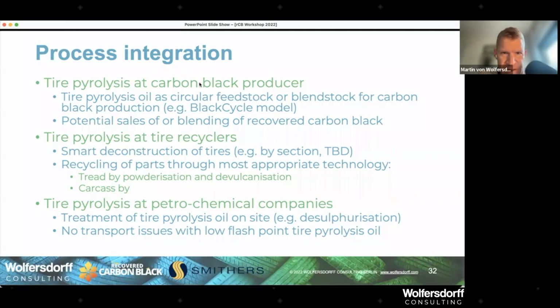Randall is asking, what is the CO2 equivalent per ton of recovered carbon black? Yes, that is exactly what I said. So it depends, of course, on the process. Do you have like 2 pyrolysis kilns, one after the other, like Black Bear Carbon, to have a super high quality recovered carbon black? Then your carbon footprint is slightly higher. I think with a range of technologies, you can take 300 to over 600 kilograms of carbon dioxide per ton of recovered carbon black as an approximate figure.